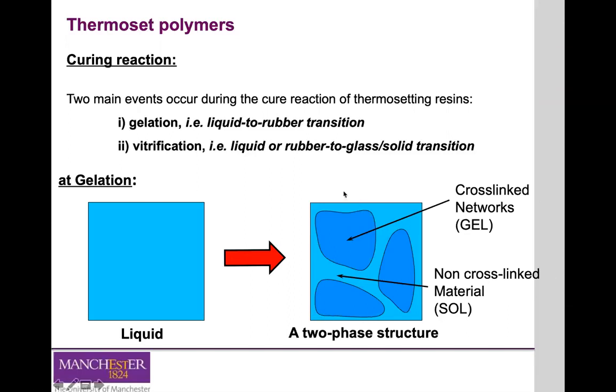At this point, where you have a two-phase structure, the system will no longer flow, and these two phases will coexist, okay? And remember that the gel phase, or the gel part, is insoluble in non-degrading solvents. But the sol phase can still be removed and degraded by solvents. And as you move from this liquid stage to this gelation stage, you have a dramatic increase in viscosity, because obviously you are forming these solid networks that will increase the viscosity of your system.